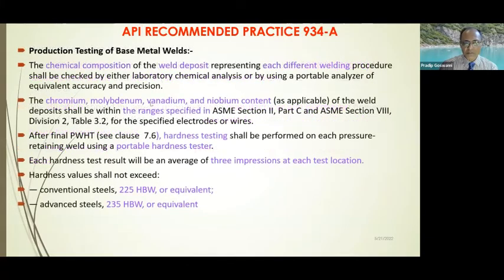So the production testing on the base metals, whatever is needed, is highlighted here. You need to have a chemical composition of the weld deposit for each welding process adopted. And in the weld deposit, the chrome, moly, vanadium, and niobium content of these weld metals should meet ASME Section 2 Part C, the applicable ASME code for welding consumables. That means, if it is SFA 5.5, the requirement of SFA 5.5 is to be followed for welding consumables. The welded joints definitely meet the alloy content, the chrome, moly, vanadium, and niobium content, to that requirement.